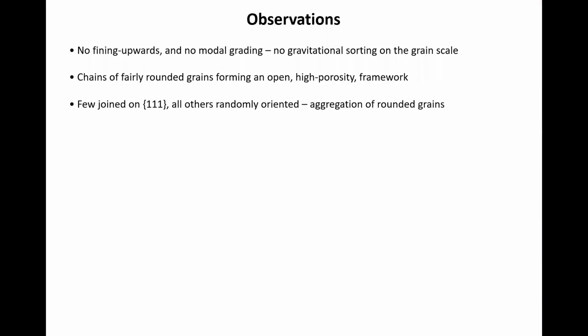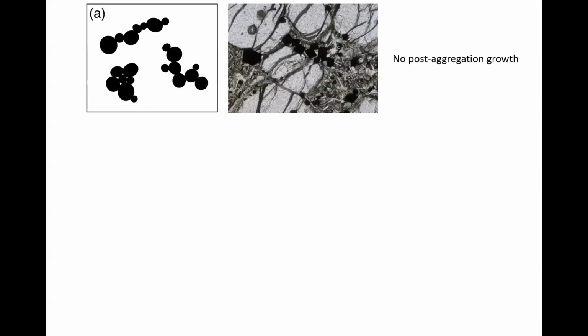Right, so these are our observations. We're stacking them up now. We've got aggregation of rounded grains to form chains, making this open, high porosity framework. Now, what happens once we've aggregated to form our chains? This is just a little cartoon here. If they just aggregate and then are immediately quenched, as indeed we have, this is just a magma chamber that was emptied out, made a little 3-meter sill, and then bam, everything just stopped. No post-aggregation growth. Then you're basically seeing the original shape of your chromites, and they're just stuck together on their 1-1-1 faces or 1-1-0 faces, and it looks a bit like this.